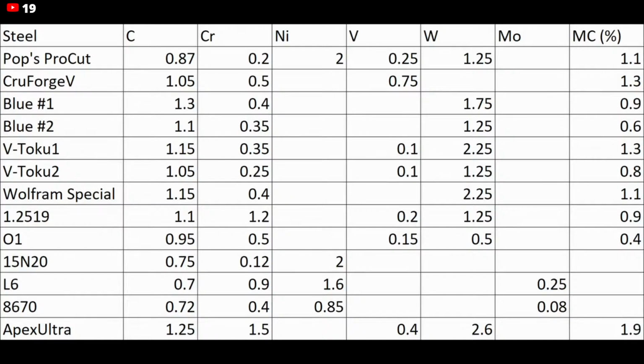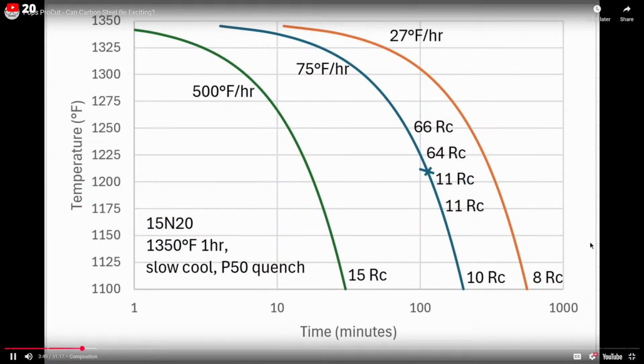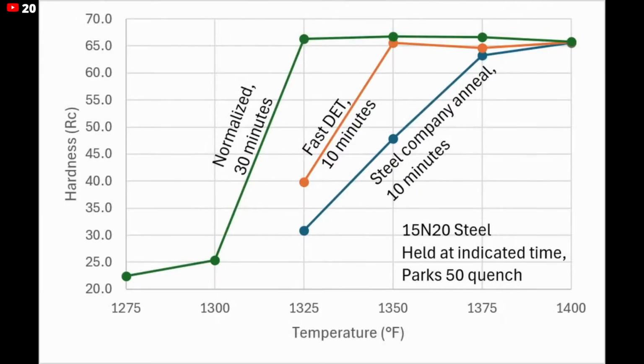So let's get something out there that everybody can buy, it's easy to use, and we have an exciting set of properties. Also, that high nickel, if we add 2% nickel to it, then it can be used in pattern welded Damascus as the bright layer. We also worked on their production annealing process, because the annealing procedure we felt was going to be very important to make sure that the steel would respond well to forge heat treating. And so we went to the mill and they made the steel, and then we started testing and we were really happy with how it turned out.